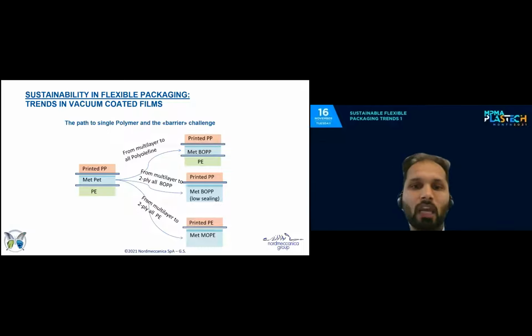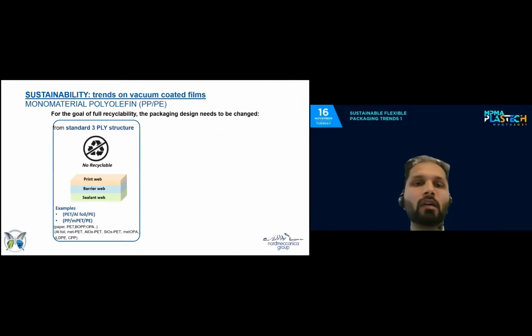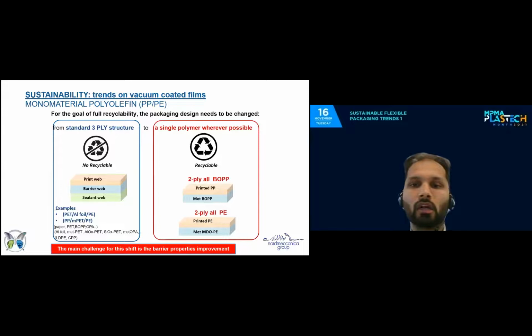So what is the aim of this new design? The standard three-ply structure is not recyclable. But if instead we move to a single polymer structure wherever it is possible, so two-ply all BOPP or two-ply all PE, the structure becomes recyclable. And the main challenge nowadays is to transfer the barrier properties from the standard ply to the new recyclable structures. And so what are the technologies that are available in order to address this sustainability?